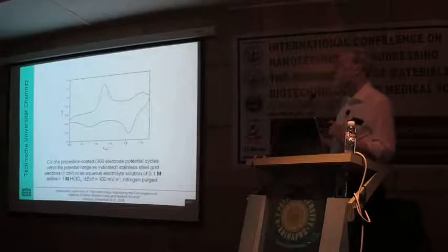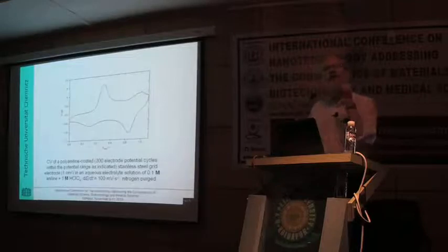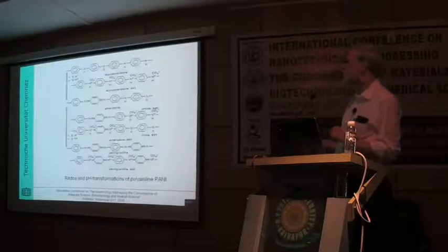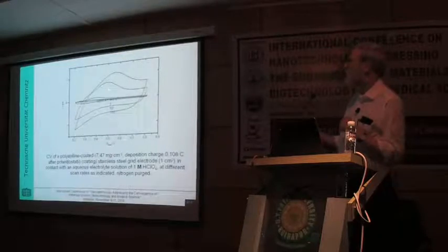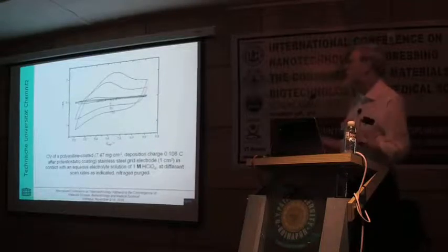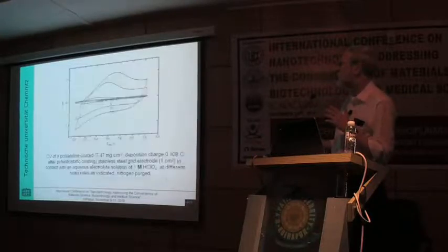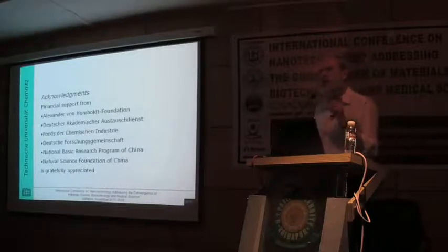But again, we also can assume in such a conducting polymer electronic interaction between these segments of different lengths of conjugation, which, this is the picture I just showed you, might also explain to some extent why with growing thickness, this is a thick deposit, it's not just a very thin layer like in the previous slide, the response also goes away from the pronounced peak shown here to a much broader peak-like appearance. So, in conclusion, the reason for this pseudo-capacitive behavior is, in case of ionic species like metal oxide,